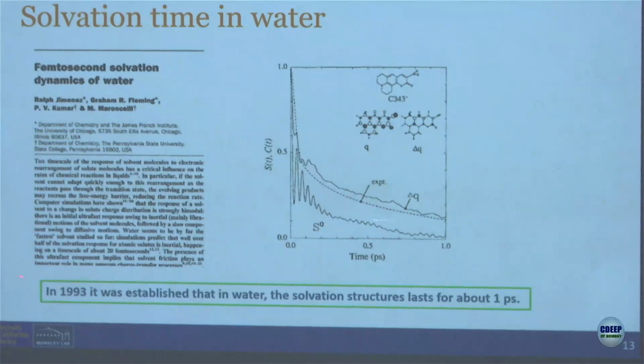In 1993, it's hard to believe, but in 1993, we got the first estimate of what that time constant might be. And in the case of aqueous systems, it is 1 picosecond. This is a paper by Graham Fleming, a professor at Chicago at that time. Beautiful 2D IR experiments that I don't understand, but if you look at this time scale, it is 1 picosecond, and the decay of the structure factor on that time scale roughly tells you that this water molecule hangs around the ion for about 1 picosecond.